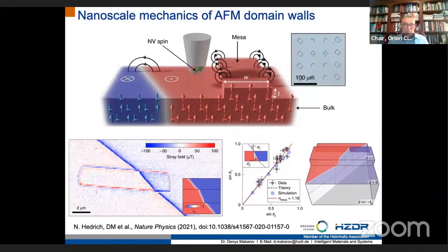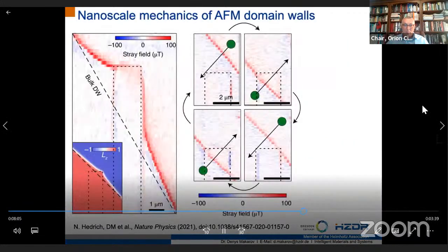Another important feature comes from the analysis of the domain wall profile in the interior of the film. As you can see from the right-hand side image, the domain wall in the sample is actually flat. It's like a plane which is deformed only when the domain wall approaches the surface of the sample. If you have such a possibility to deform only the domain wall at the surface of the sample, then you have an interesting possibility to manipulate the domain wall and use it for some recording application.